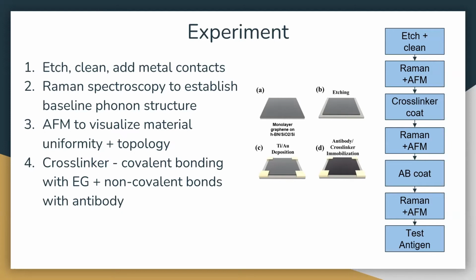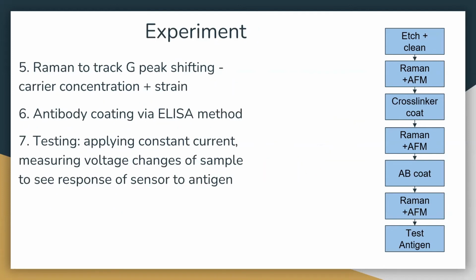I first etched, cleaned, and added metal contacts to each of my samples, then conducted Raman spectroscopy to establish a baseline phonon structure, and then did atomic force microscopy, or AFM, to visualize the material's uniformity and topology. Then I coated each sample with a crosslinker, which serves to covalently bond with the epitaxial graphene and non-covalently bonds with the antibody. This allows us to actually clean off the antibody using a sodium chloride solution very easily.